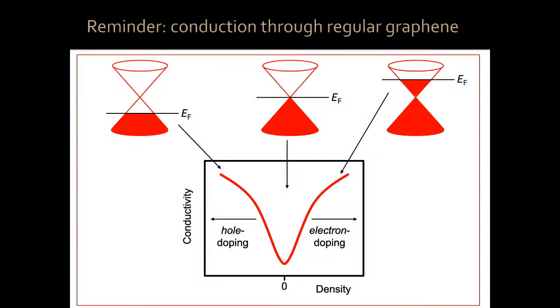So before I show you data about magic angle graphene, let me remind you what conduction through regular graphene looks like. If you measure the conductivity versus charge density for regular graphene, just monolayer, if you have your Fermi energy deep in the valence band, you have lots of holes, so it conducts very well. If your Fermi energy is deep into the conduction band, you have lots of electrons, so it conducts very well too. And if your Fermi energy is at the charge neutrality or Dirac point, you have very few charge carriers, so you conduct poorly. So the conductivity of graphene versus charge density has this V shape, which has been seen and measured by thousands of groups around the world for many years.